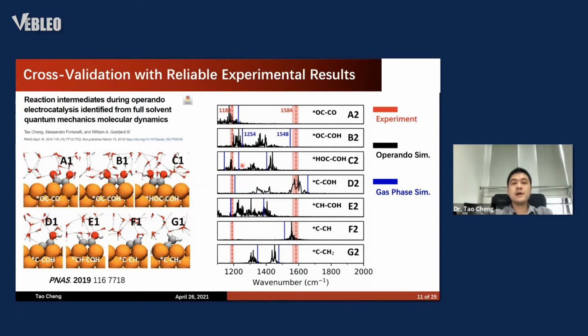So here I show that we can also do these predictions for the spectroscopy. In this case, the spectra cannot be directly compared with experiment, because experimentally it's even impossible to see the reactive intermediate, but it's possible to have this spectroscopy. So here I show when you compare the experimental results with the simulation results, the black one, we can see that we can identify CCOH as an important reactive intermediate in our reaction pathway. So this is strong evidence showing that our prediction is reliable.